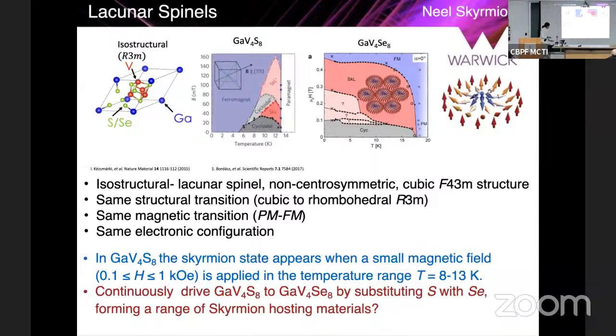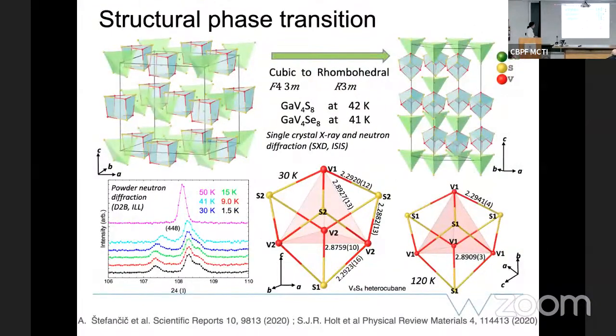So is that possible? The first thing to do then is to study the parent materials to start with. If we take the parent materials, gallium vanadium 4 sulfide and the selenide, and you look at the structural transition that takes place, the sulfide undergoes a structural transition at 42 Kelvin, and the selenide material undergoes a structural transition at 41 Kelvin. So they're very, very close to each other. What happens exactly at this structural transition?